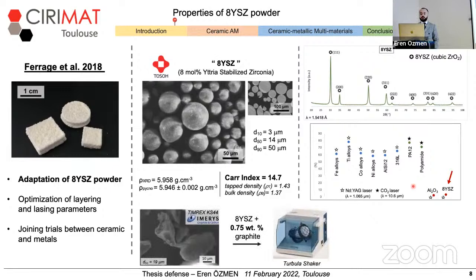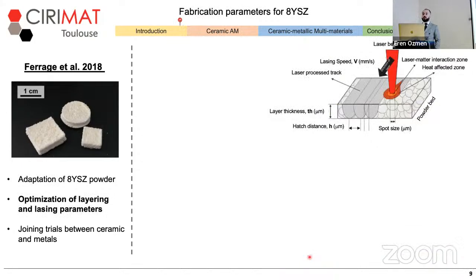To overcome this issue, the ceramic powder was mixed physically with 0.75 weight percent graphite in a Turbula shaker. And then after this enhancement process, the absorbency was increased up to 60%, and the flowability was not affected by this process. Once the powder was ready for operation,